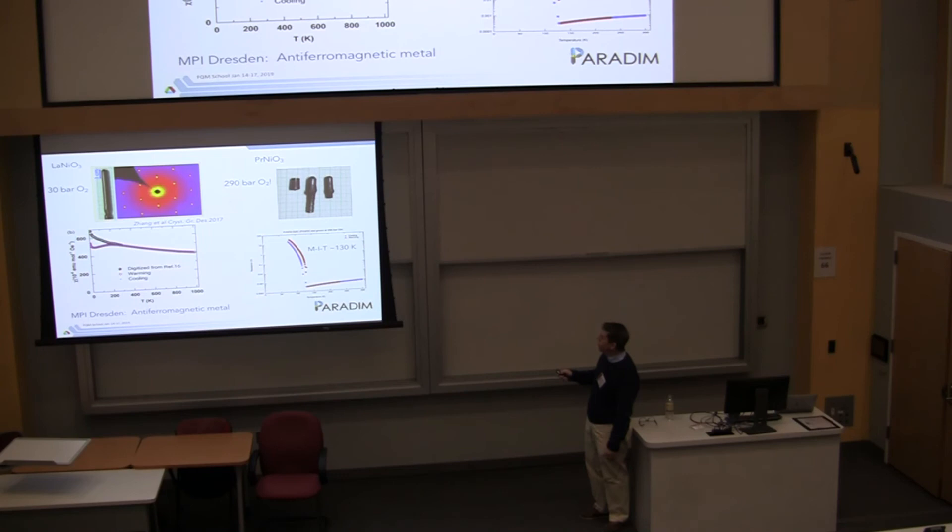And if you, and we use neutrons to explore that. And what we found is that the propagation vector for the spin and the charge order are in this two-to-one ratio, this magic two-to-one ratio that's found for spin stripes. And so there's some sort of long wavelength stripe, I think, that's forming in this material that we couldn't see before. And the reason we never saw long range order using neutron diffraction powders is that the intensity of these little spots is five or six orders of magnitude below what we see below the Bragg spots, the main Bragg spots.